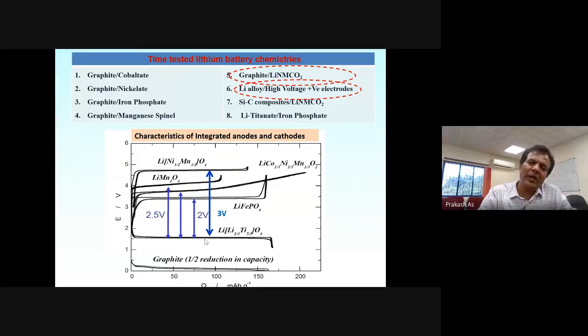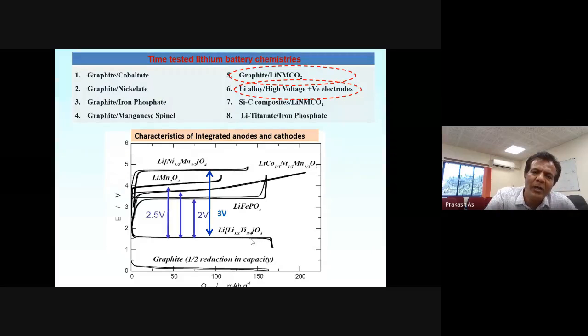Let us say, for example, lithium titanate is another anode or negative electrode material. If you are using lithium titanate versus the same lithium nickel manganese oxide, this potential is about 1.5 volt. Then the difference between the potentials of positive and negative is 4.5 volt minus 1.5 volt. So you get about 3 volt here. Similarly, lithium iron phosphate versus LTO gives 2 volt.